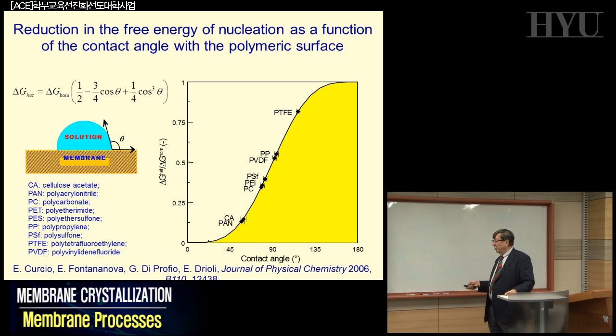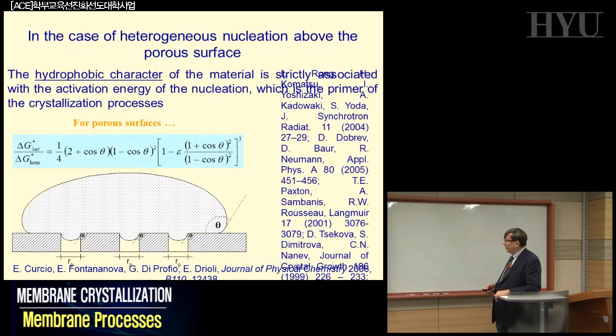So this second effect, very important, is that the activation energy of your system can be significantly reduced as a function of the hydrophobic character, that means the contact angle of your membrane. So if the contact angle is increasing, arriving at superhydrophobic membranes, you can still have a higher reduction of the activation energy. That means speeding up the formation of your crystals significantly. That's quite an interesting effect that is under investigation today. Everybody is now looking into this and trying to find membranes that work not only as a function of the intrinsic hydrophobicity, but also of the apparent hydrophobic character, by checking the roughness of the surface and the distribution of the pores. All these effects are quite interesting because they can create the situation for this kind of effect.